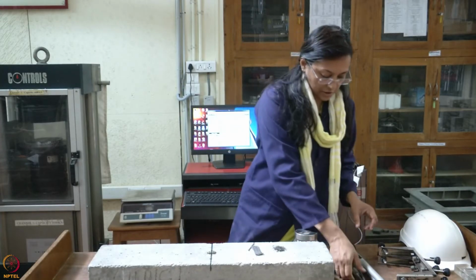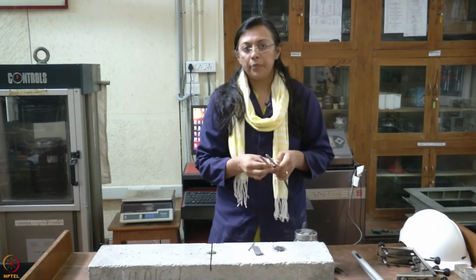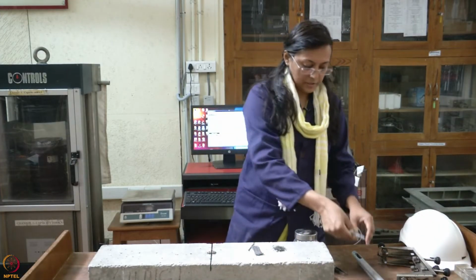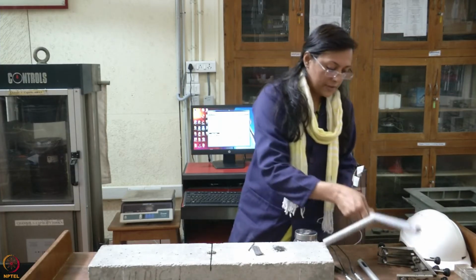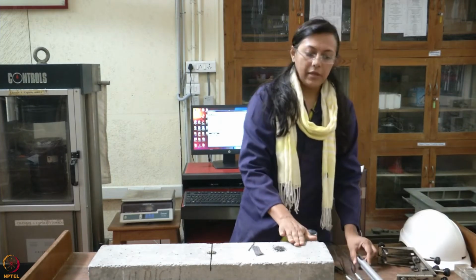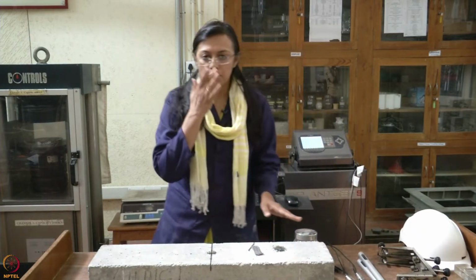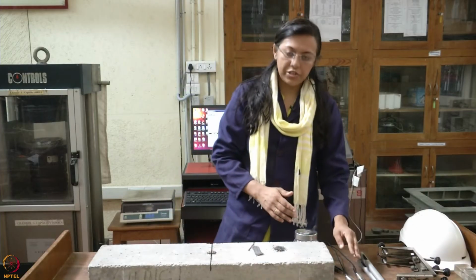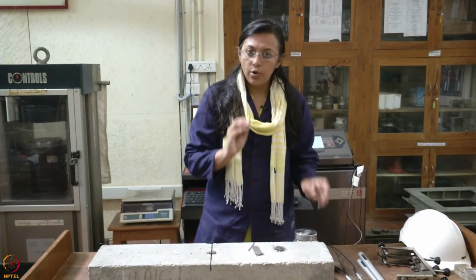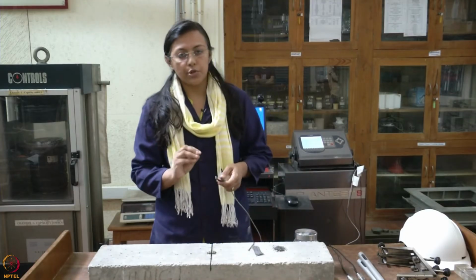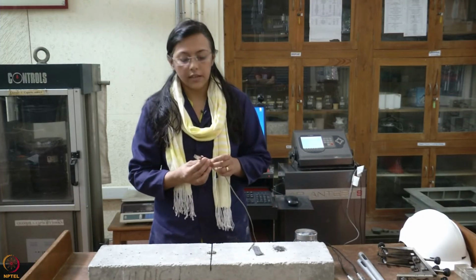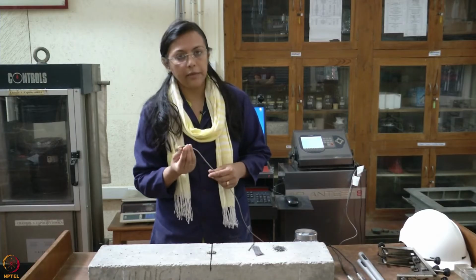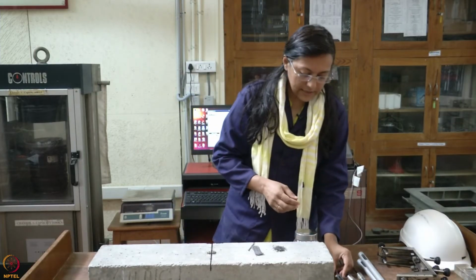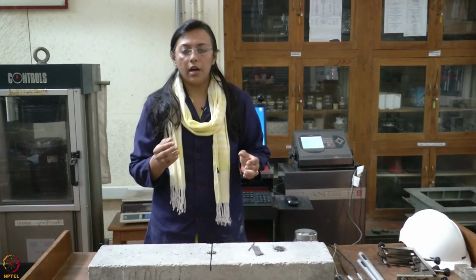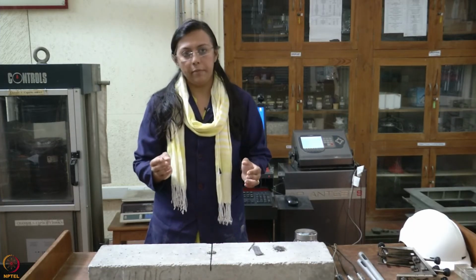But along with crack opening, we are even measuring deflection. Deflection is measured by two LVDTs, which are mounted on either side of the specimen using this frame, and this frame is fixed onto the specimen by means of a C-shaped collar. Although we are measuring deflection and crack opening, the control parameter, as this is a displacement control test, is the CMOD, which is measured by the clip gauge. This test is continued until a crack opening of 4 mm.